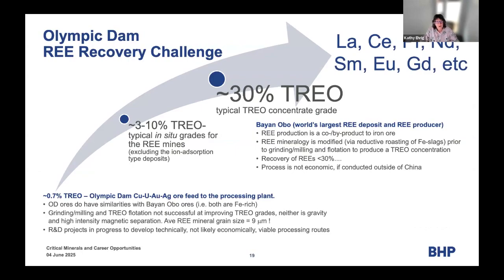So the Olympic Dam, the rare earth challenge, and it doesn't mean we're ever stopping, and the journey that most places in the world start, really at roughly this 3%. It's dropping down a little bit, 3% to 10% total rare earth oxides in their ores going in. They then get concentrated up to roughly that 30%. These days it could be 20, maybe a little bit higher than that, maybe a little bit less. And then that rare earth concentrate goes into a solvent extraction process in order to extract them all.